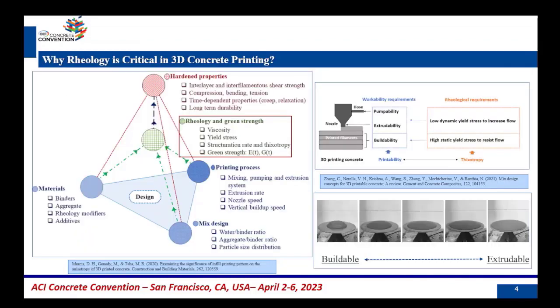So if we talk about 3D concrete printing, rheology and green strength, it is very critical to control both of these parameters. And Mechtcherine et al. suggested a tetrahedral model to discuss how different factors are interdependent on each other, and they place the green strength and rheology right at the center, analogous to the oxygen atom in the silica tetrahedron.